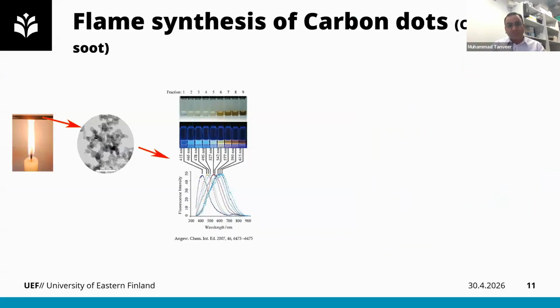Flame-based methods lie under the category of bottom-up synthesis routes. And in this technique, basically, we control the combustion condition. We introduce fuel-rich conditions in our system and then control the atmosphere and produce the carbon dots or carbon nanostructures according to our need.